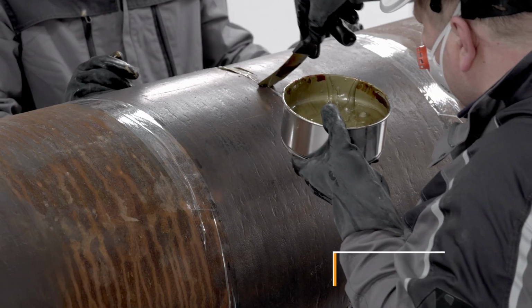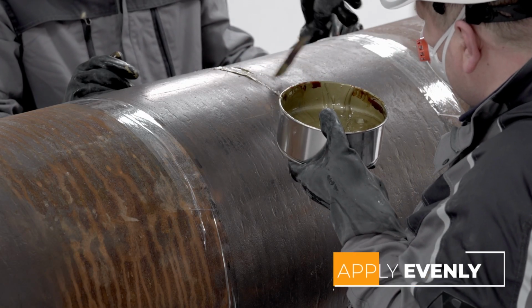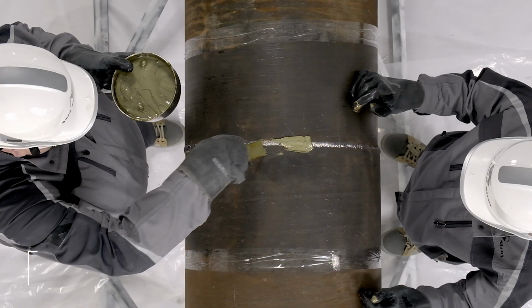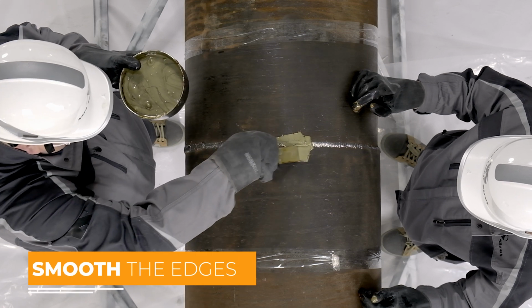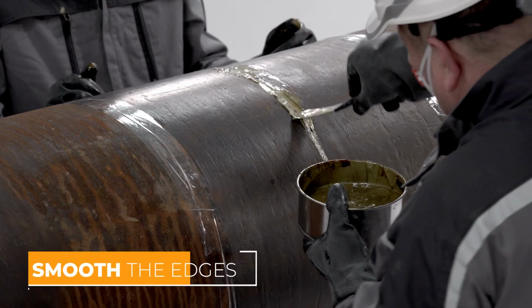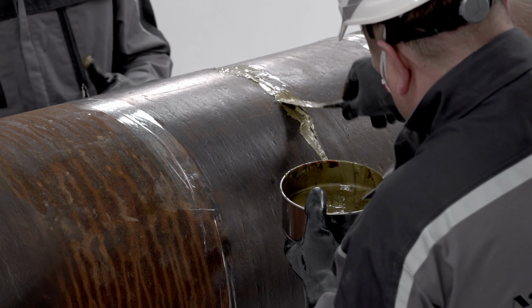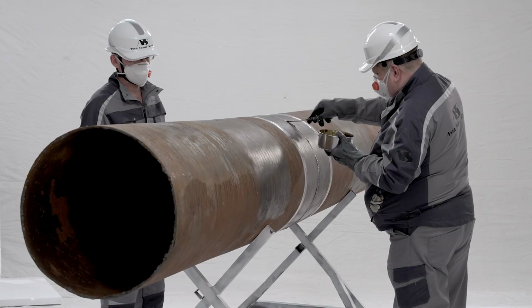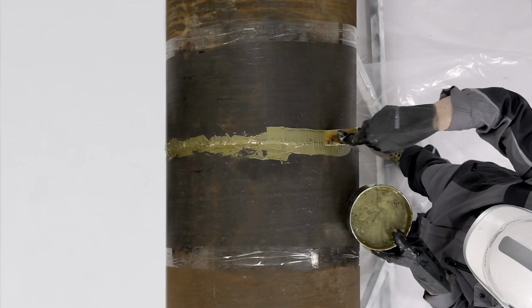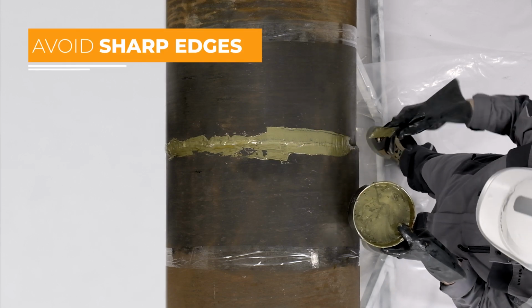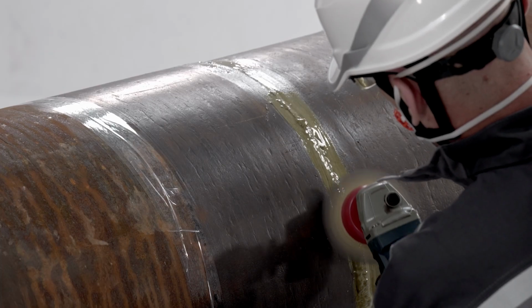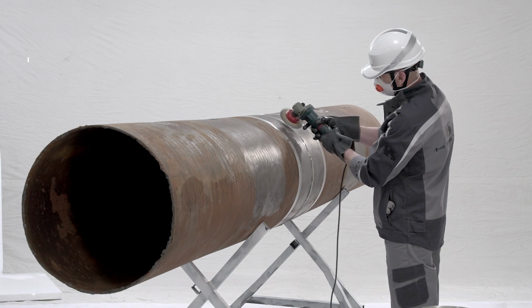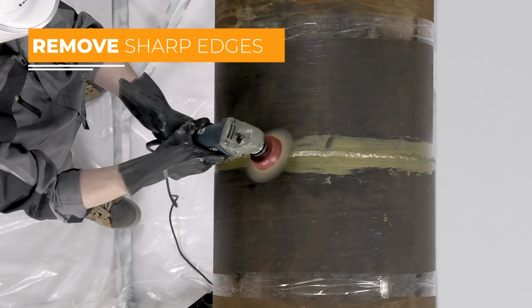Applying the paste to the joint. Use a spatula to apply the paste evenly to all voids and areas related to defective areas. These areas should be smoothed to create a smooth transition when installing the coupling. Smooth the paste so that it follows the contour of the pipe as well as possible. Avoid forming sharp edges. Use sandpaper or a sanding tool to remove any sharp edges.